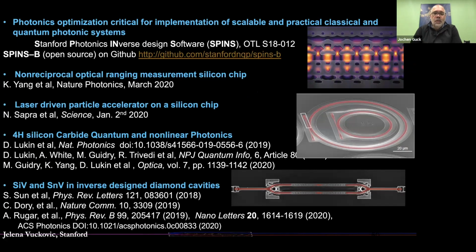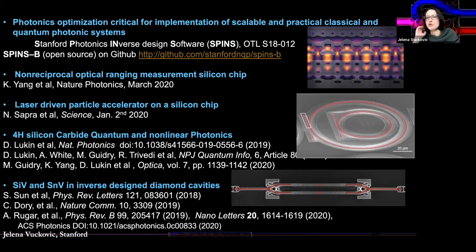So one is, since you are leveraging Chi3 nonlinearities in the non-reciprocal isolators, I'm assuming that the device is intensity sensitive. Does it require a threshold power for operation? Yes. There is what I was referring to as a dynamic power range. There is a range of powers in which it works. So definitely there is a sensitivity in terms of the input power, but it is a pretty broad dynamic power range of operation. And we did a detailed analysis of that in the paper. Having said that, you can design it for a particular dynamic power range that works for your applications. And it's a pretty broad range. So if your power fluctuates, you still do see the same behavior.